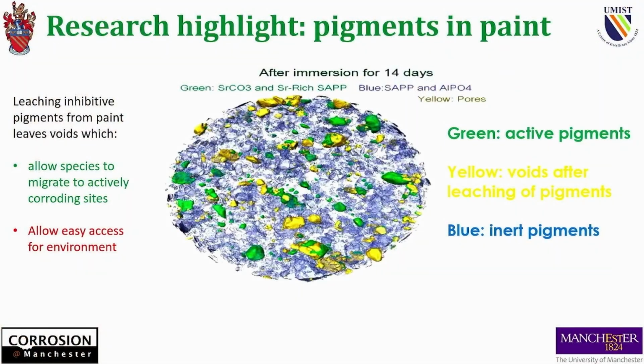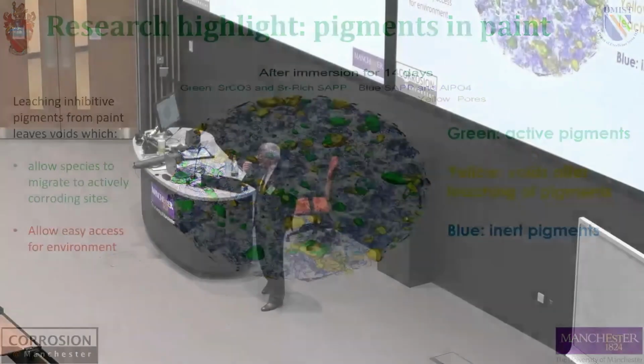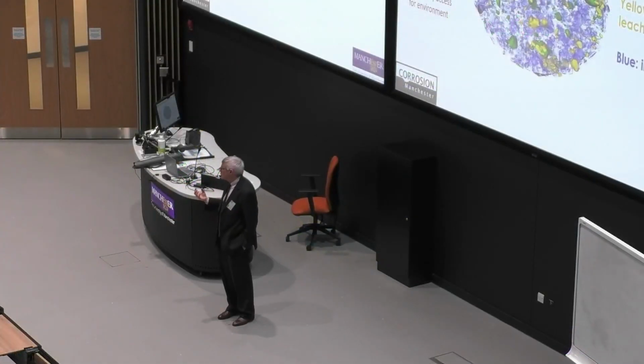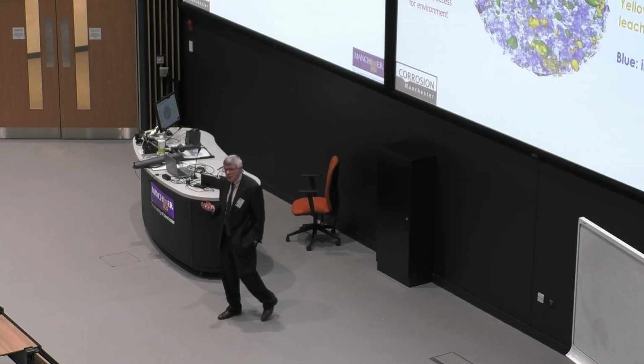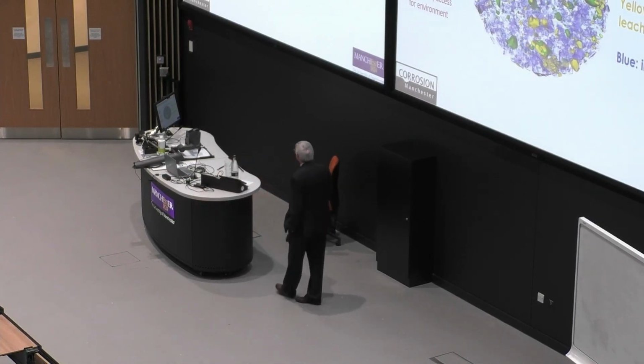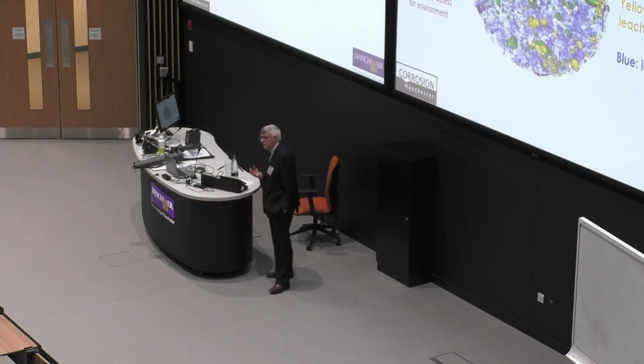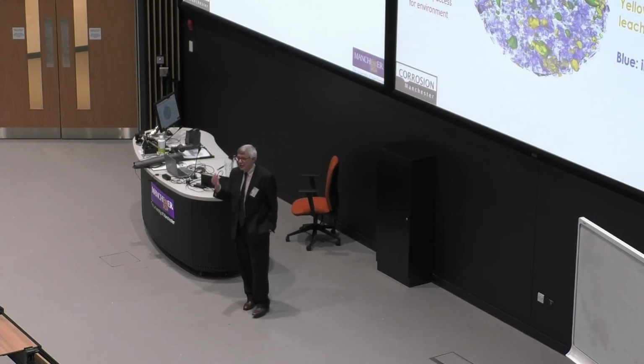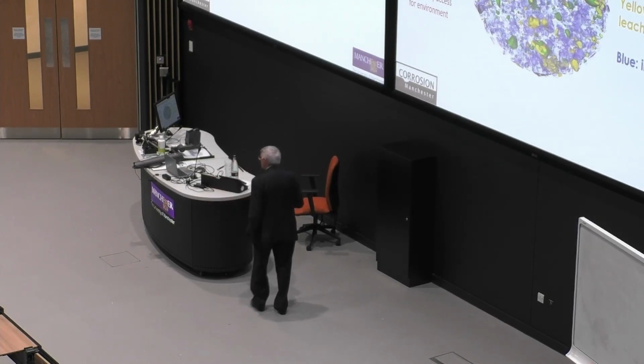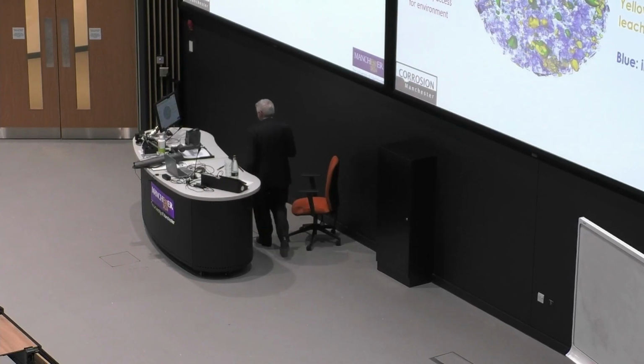But again, knowing this, we can now design the paint or the pigmentation to have the correct size, the correct morphology, the correct spacing. If it's too far apart, the pigments don't dissolve, because the water never gets to it. If there's too much pigment there, then we create huge, great big gaps. So there used to be an idea that the more pigment you put in, the better inhibited. That's not the case. There's a sweet spot. Now we know what it is. We can design for it.